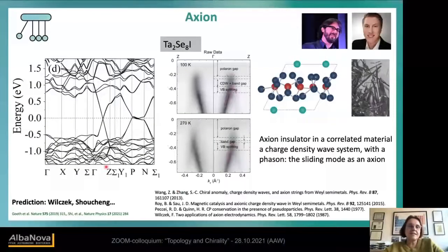Anyway, the starting point was that we looked for chiral crystals, and this is a chiral crystal, by the way, and for new fermions, and tantalum selenium iodide was a candidate material. So we did the band structure calculation, and we thought, wow, this has such a nice band structure. It's an ideal Weyl semimetal, because we have quite a big gap here, and the only bands which are crossing are the bands which lead to the Weyl crossing. So this was super exciting for us.